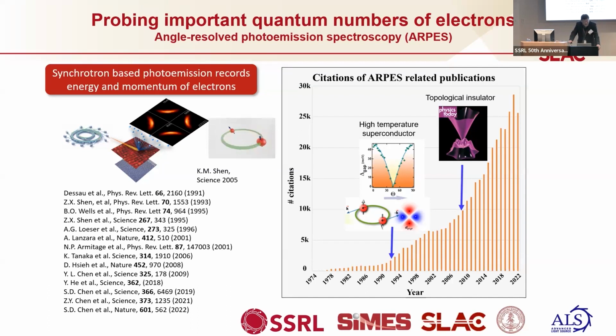For a superconductor to have its superconducting properties, you need to take two electrons and make them form a pair. How they pair will tell you a lot about the mechanism of these systems. In conventional superconductors, you can think about them being paired symmetrically, so-called S-wave, which means that the superconducting gap should have been a constant. And in the novel superconductors, it turned out they pair asymmetrically in the D-wave channel. This detection shows that angle resolved photoemission can be a quantitative tool to answer a question whose answer is a priori unknown.